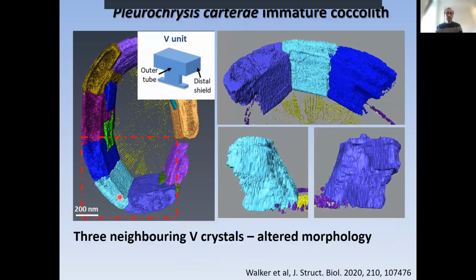that are adjacent, where what we're missing, especially if you look at this blue crystal in the middle here, is that instead of having these indentations in the middle from kind of a T shape, it's just flat on the side, and that is because we don't have an R unit growing next to it that would be restricting the growth of the crystal to the side.